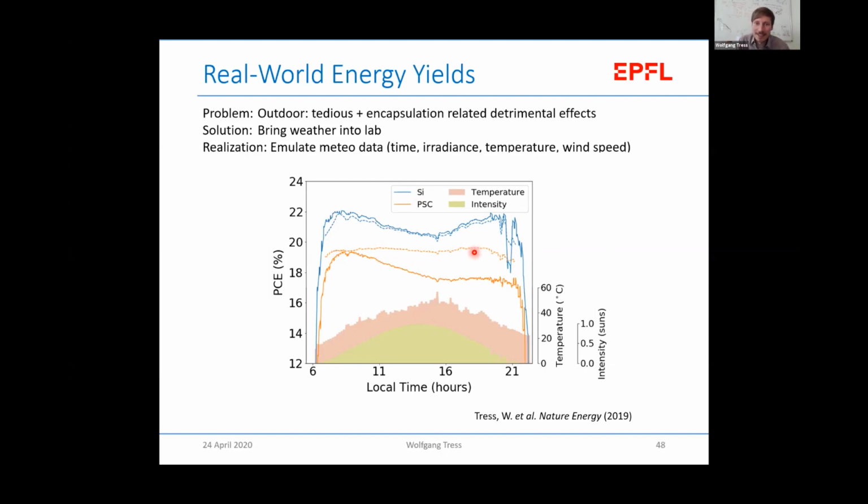So at higher temperatures, we lose a little bit in the voltage, but we might gain a bit in the fill factor, which is related to resistive effects, which we can remove a little bit. And here you can see that the efficiency drops indeed. This is this reversible effect. The next day it would basically go up again.